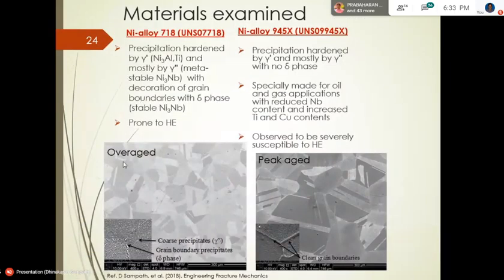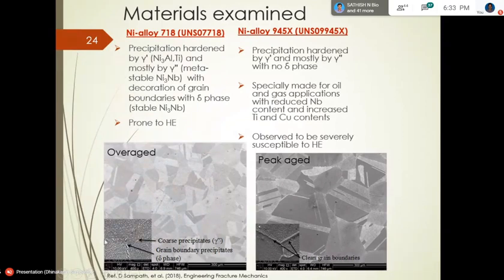So here, this 718 has gamma prime and gamma double prime precipitates. The major strengthening is coming from gamma double prime. They are of the size of hundreds of nanometers, sometimes even less. If it is in overaged condition, we saw something around 80 nanometers gamma double prime on average. And this also has delta phase at the grain boundary. In this inset I'm showing, on the boundary they have delta phase, which is actually deleterious.